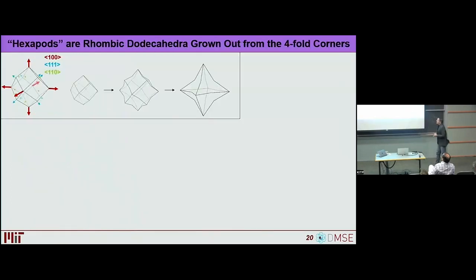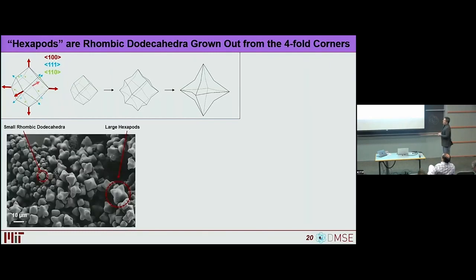Firstly, why these hexapod type structures? That one is fairly easy to explain. The rhombic dodecahedron is the Wulff shape for a BCC type lattice. But if you take that Wulff shape and you grow out specifically along these 100 vectors at these fourfold corners, it gradually transforms into a more stellated hexapodal type structure. So mechanistically, this is what's going on. We must be starting out with something that looks like a rhombic dodecahedron, but for some reason we grow faster at these fourfold tips than other directions. We can verify this by taking a simple sample.